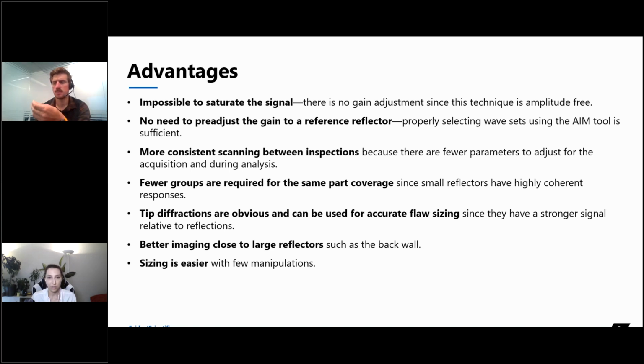There's a better imaging of large reflectors, so especially back walls, and again we'll see some pictures of that. With an amplitude-based technique, often the back wall is very loud, and if there's a reflector or some indications that are very close to the back wall, it can be hidden or the resolution might not be great. So this is another advantage of the PCI technique. And of course, sizing is easier with fewer manipulations, and that we'll look at as well. Typically, it's very easy to see where the cursors will go, and it makes for a very fast analysis.